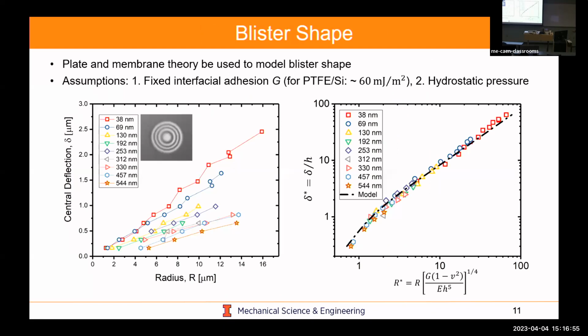And so we use pretty simple top view optical microscopy. We limit the wavelength so we could actually do fringe counting. And so you could actually get things like central deflection of this blister as it grows. So delta would be at the center. What is the height as a function of the radius for different thicknesses of material? And then you could actually normalize this by the thickness of the material by this delta star. And this normalized radius actually comes from something called plate and membrane theory, which is a mechanics theory developed long ago, 60 or 70 years ago. And so you get nice behavior between the physics, and it tells you that plate and membrane theory is something which is very important for the deformation and formation of these blisters.